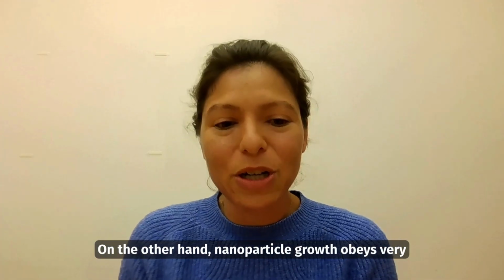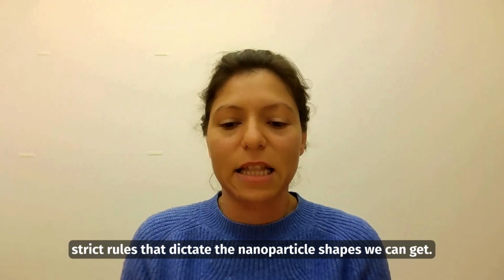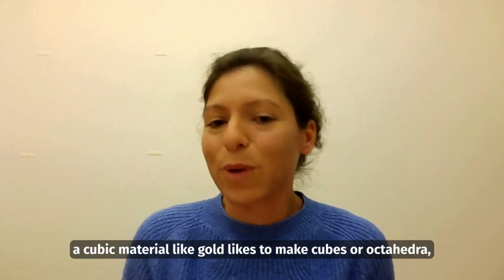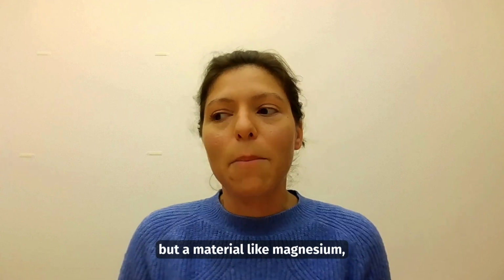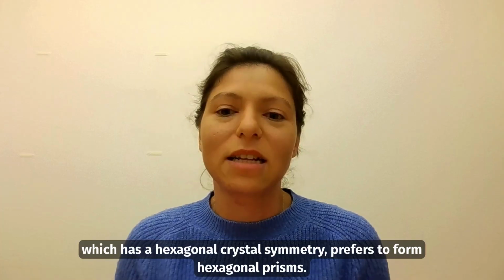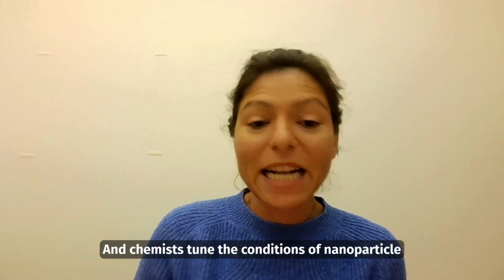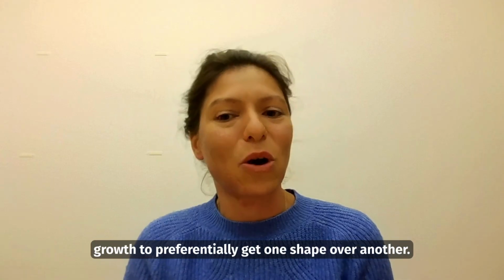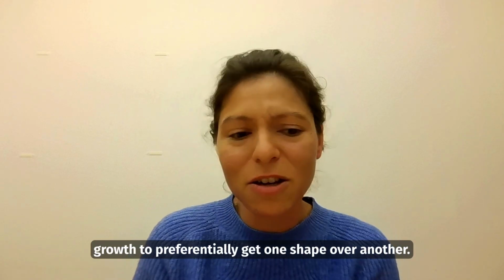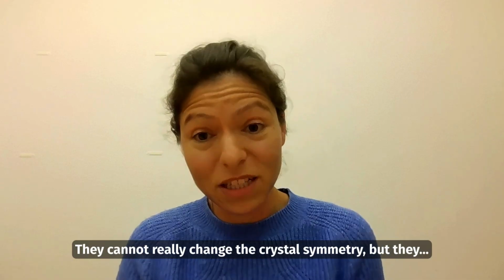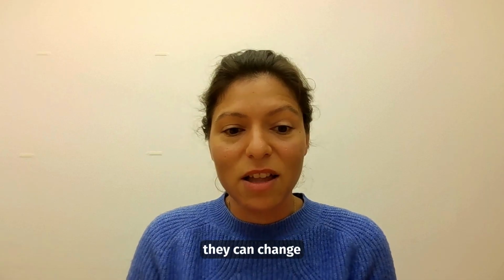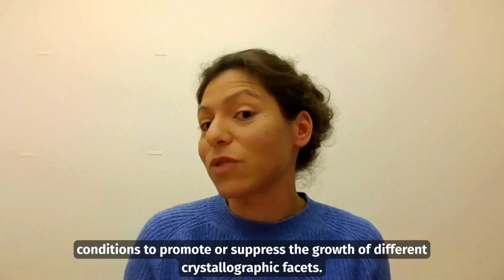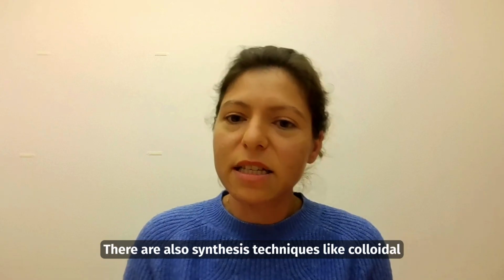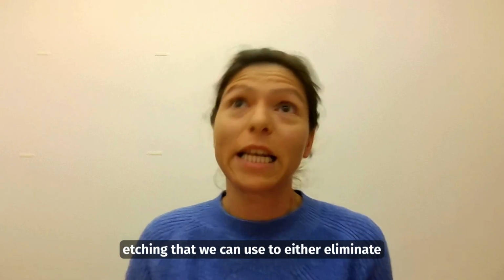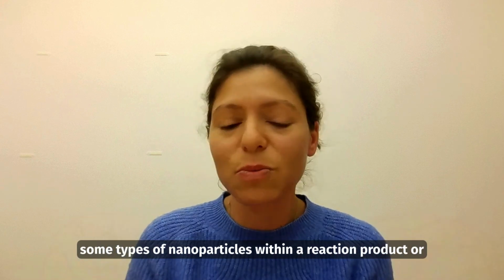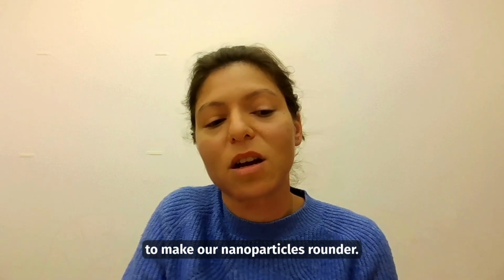On the other hand, nanoparticle growth obeys very strict rules that dictate the nanoparticle shapes we can get. So for example, a cubic material like gold likes to make cubes or octahedra, but a material like magnesium, which has a hexagonal crystal symmetry, prefers to form hexagonal prisms. And chemists tune the conditions of nanoparticle growth to preferentially get one shape over another. They cannot really change the crystal symmetry, but they can change conditions to promote or suppress the growth of different crystallographic facets. There are also post-synthesis techniques like colloidal etching that we can use to either eliminate some types of nanoparticles within a reaction product or to make our nanoparticles rounder.